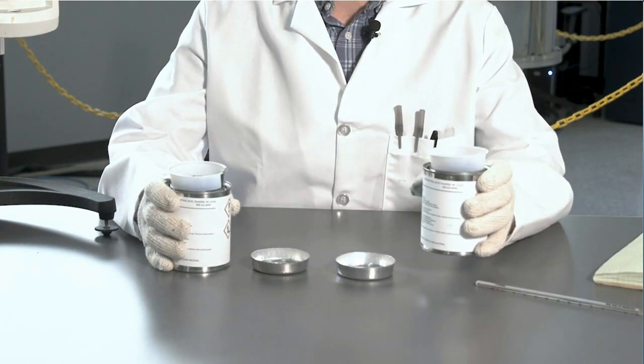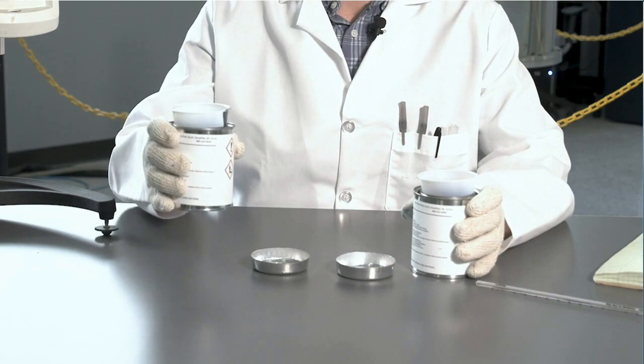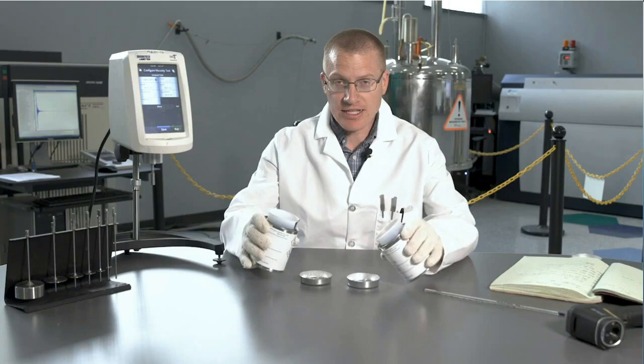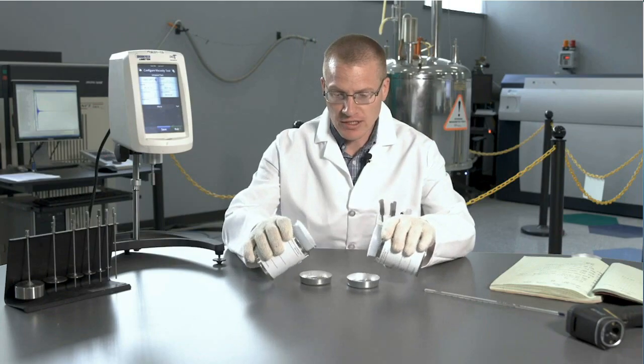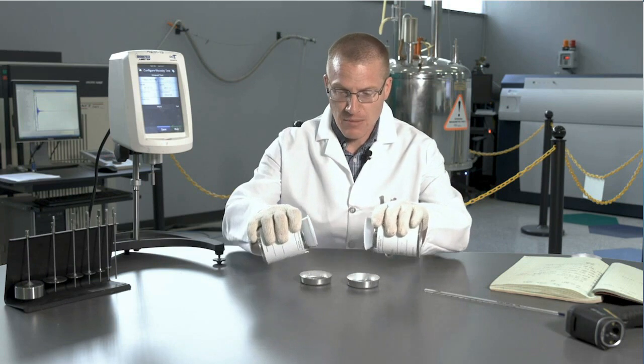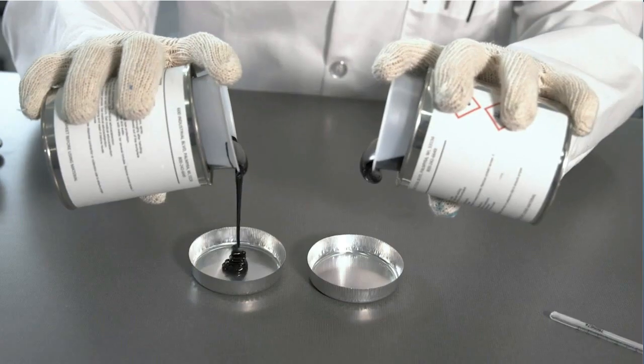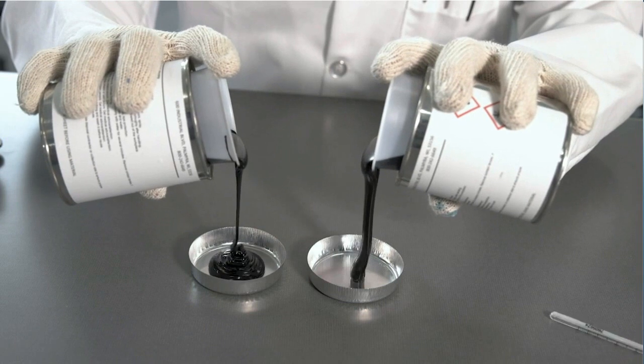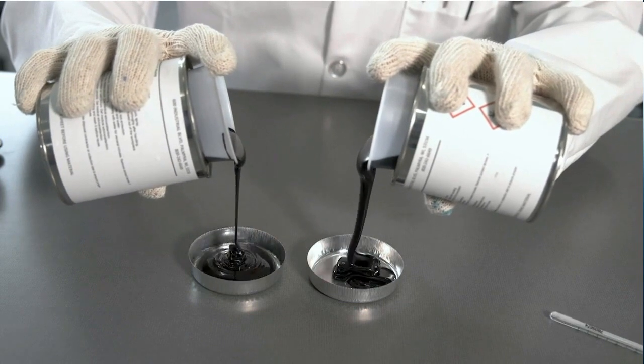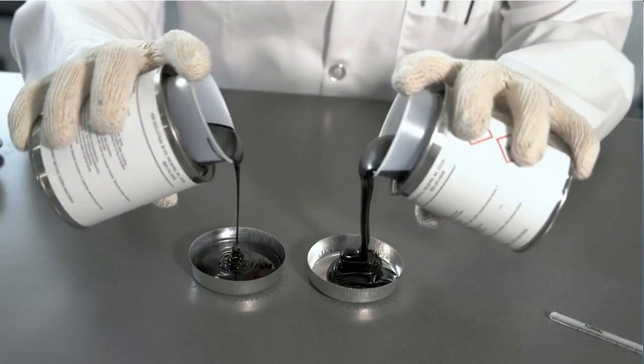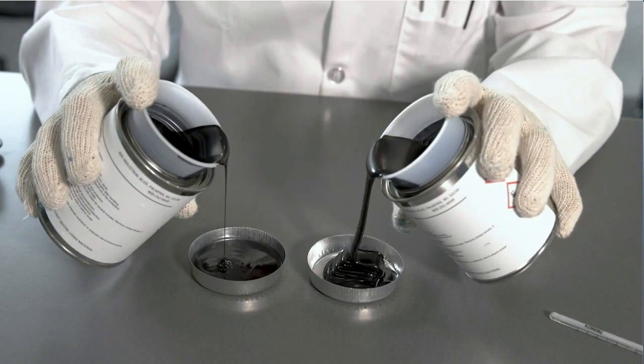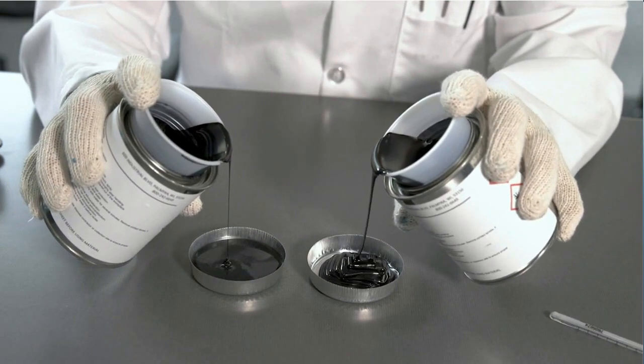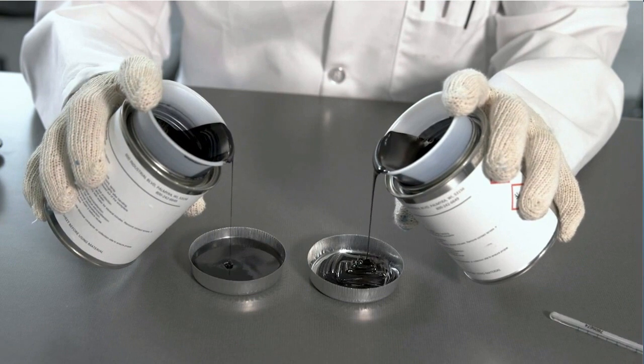This material is at room temperature. This material is at 50C. As I pour them, you'll see that one pours much easier than the other. And that shows how temperature, like we showed in the graph a moment ago, can significantly impact the flow and the viscosity of the material. Viscosity and temperature are very important factors to consider when developing your potting process.